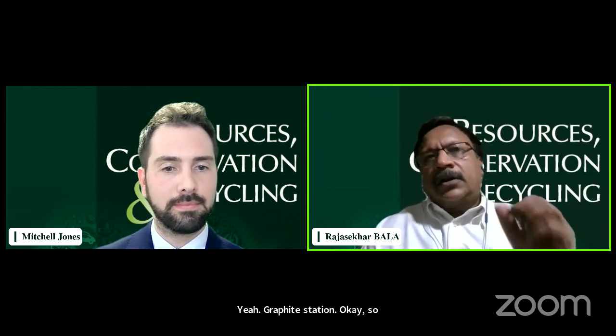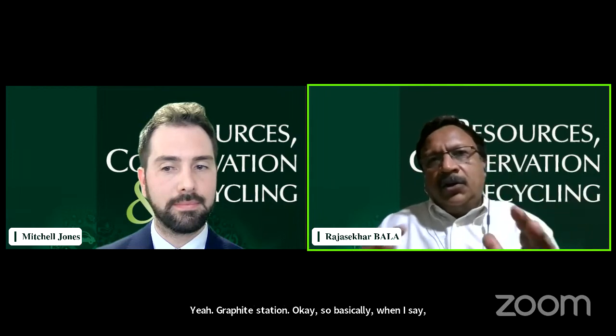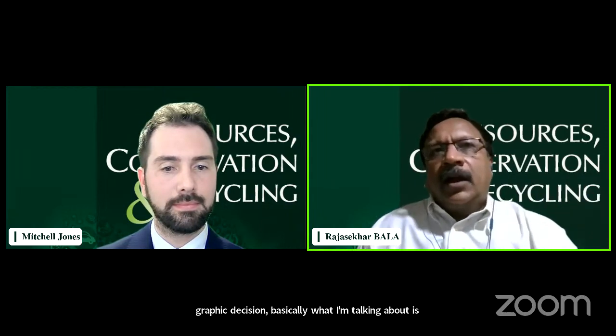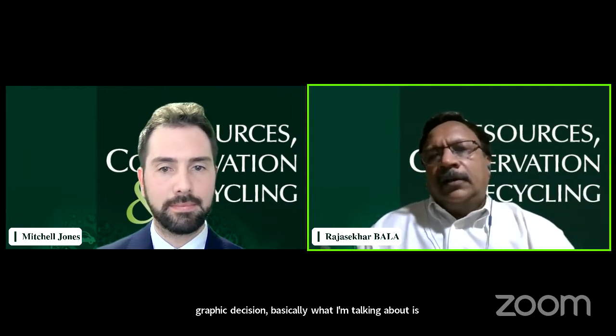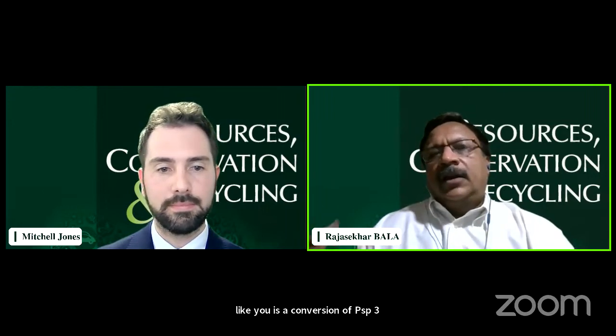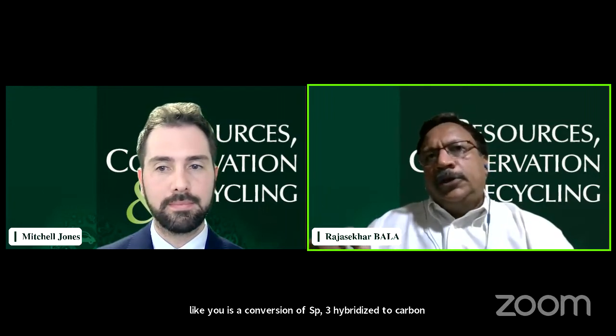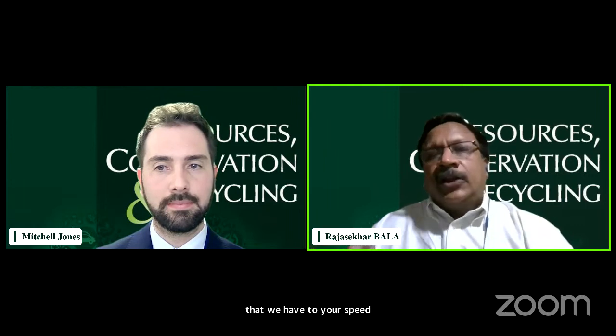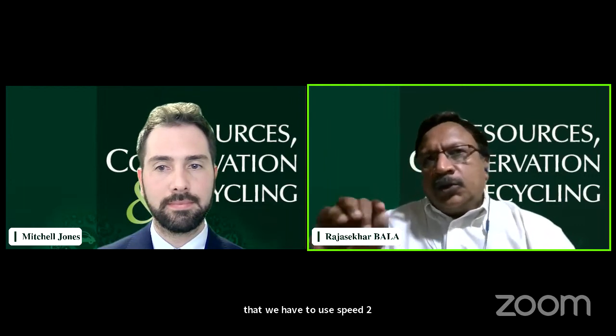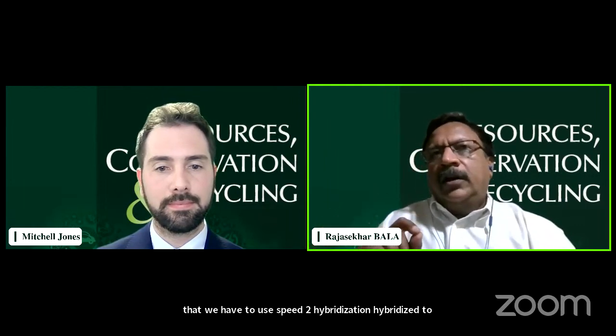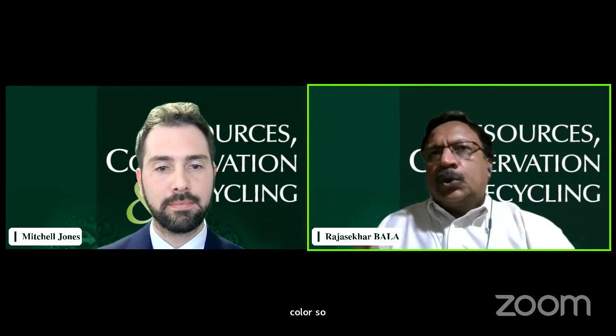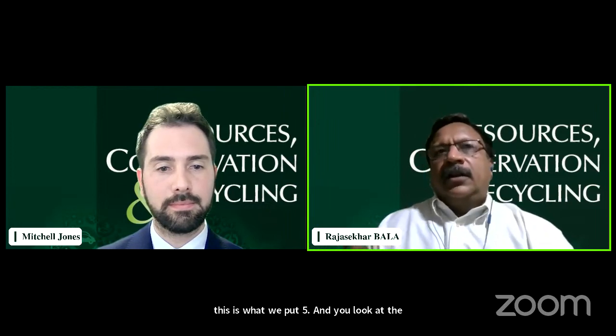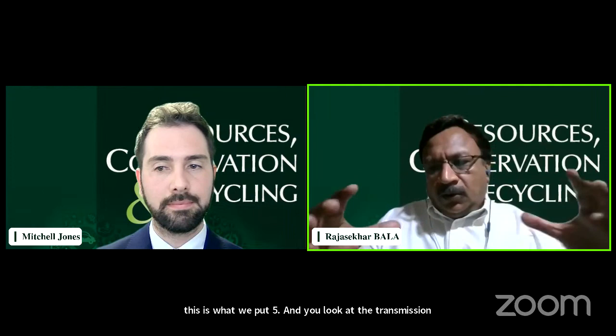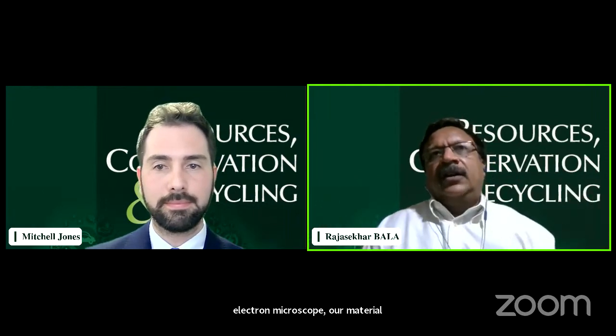Graphitization. Okay, so when I say graphitization, what I'm talking about is a conversion of sp3 hybridized carbon that we have in lignin to sp2 hybridized carbon. This is what we could find when you look at the transmission electron microscope image of our material, and you could see something more like a graphene-like material, right?